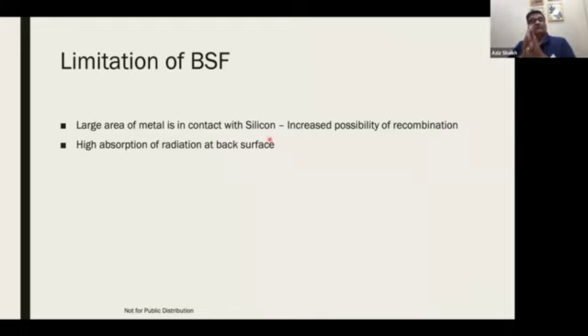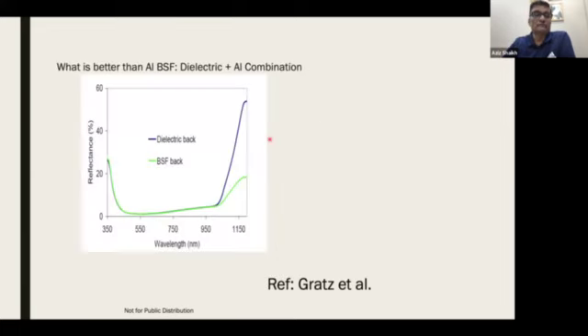But there is a limitation of this technique, which lasted for quite many years, 15 plus years. The main issue here is that a large area of metal is in contact with silicon, because a lot of aluminum is in contact with silicon. So it increases the possibility of recombination. Somehow we have to stop this if we want higher efficiency. And then there is absorption of radiation at the backside in the aluminum film.